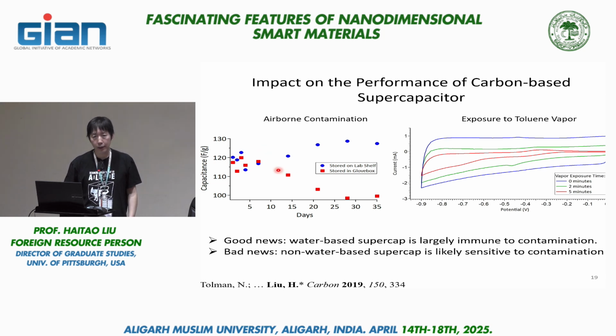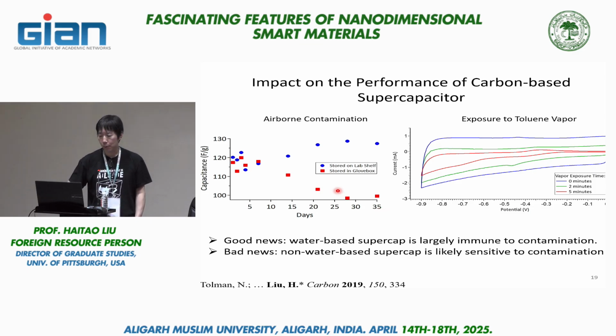Now, however, if you expose them to a dry environment, for example, a glove box, now we start to see this decline in the double layer capacitance, about 20%. So still pretty significant, but not 50%, and seems to be not an issue if you work with the aqueous electrolyte system. Okay. Now, the red data, which suggests this decline of performance in the dry environment, is also alarming because a lot of supercaps involve not aqueous electrolyte, but rather organic or ionic liquid kind of electrolyte. And in those cases, the surface contamination might be relevant.